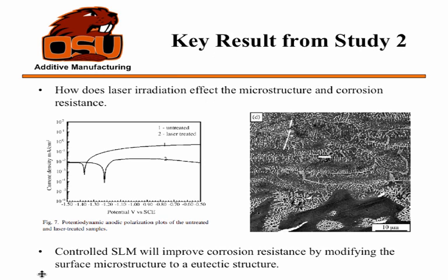And they were able to look at, this is a chart off to the left. I am not 100% familiar with corrosion, but evidently the laser treated is lower, so it has a lower corrosion factor, or is more resistant to corrosion than the untreated, which is on top. And that's the microstructure that they were able to produce. So it has a very fine eutectic alpha beta microstructure, and they found at different laser powers and scanning speeds they were able to actually control the growth of alpha versus beta microstructures.